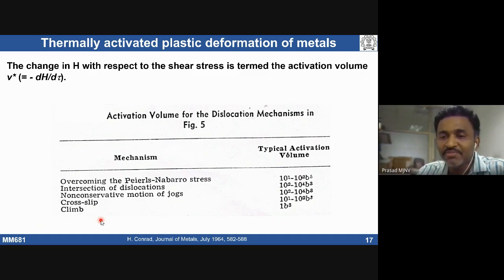The rate controlling mechanism, how do you assess it? By determining the activation volume. Activation energy also gives some indication, but activation volume can tell you what kind of rate controlling mechanism operates for a particular plastic deformation mechanism. So whether it's cross slip or climb which is controlling the overall plastic deformation of a material, one just has to determine the activation volume. I'll stop it here.